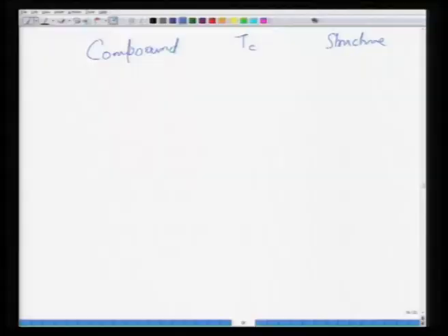So the first thing you have is yttrium based, which is of course YBa2Cu3O7. Now, I am not giving the non-stoichiometry here. Most of these oxides show superconductivity in some sort of non-stoichiometry, and the highest TC achieved was 92 Kelvin, and this has an orthorhombic structure.